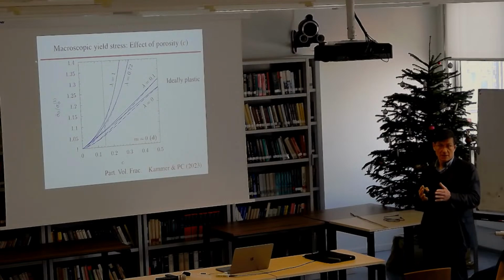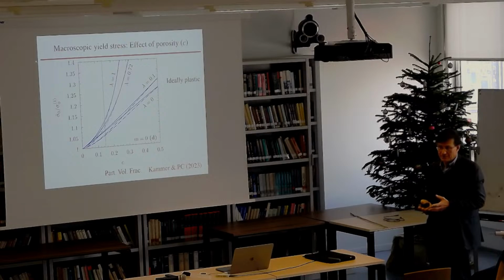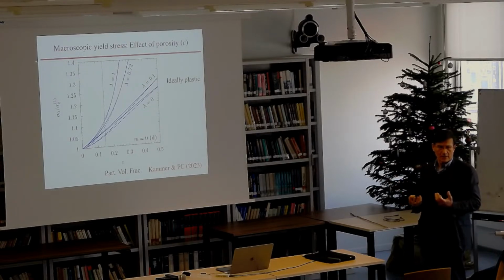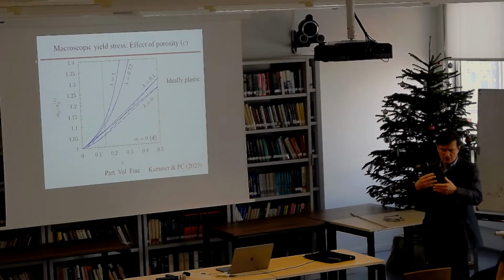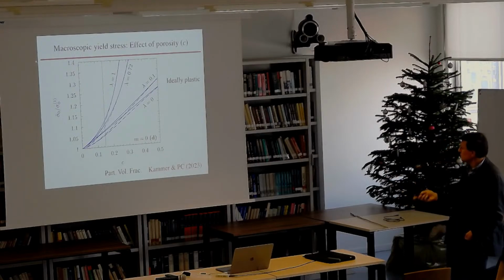This is because if you have enough particles, the bands have to meander around so much that the fields become more homogeneous, because the bands not only have to meander, but they also broaden when you go around particles.